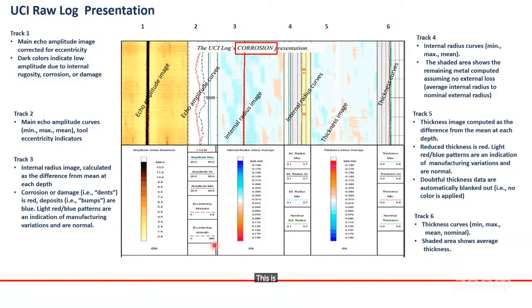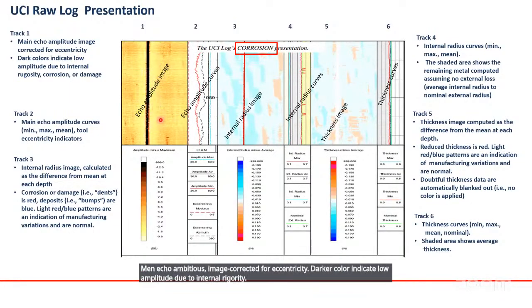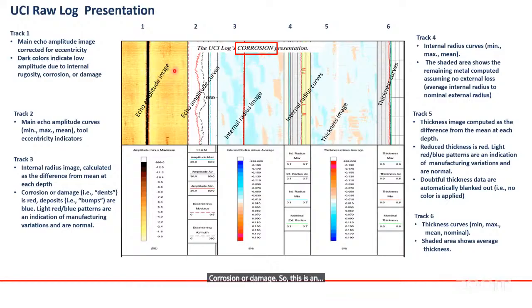This is the UCI log presentation. Track 1, main echo amplitude image corrected for eccentricity. Dark color indicates low amplitude due to internal rugosity, corrosion, or damage. So this is an echo amplitude image. Track 2, main echo amplitude curves: minimum, maximum, mean, and tool eccentricity indicator. This one is for the eccentricity indicator.